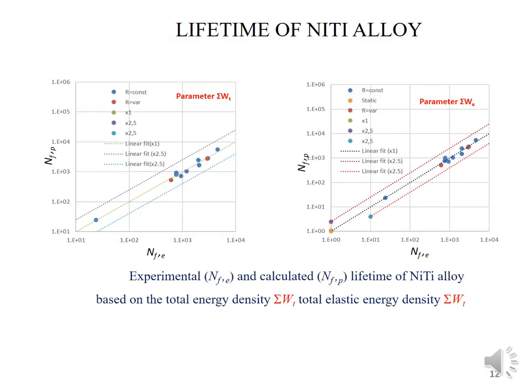Lifetime comparison of Pseudoelastic NiTi alloy, determined from experiment and calculated by the criterion of total energy density (left) and elastic energy density (right), is presented. The difference between these criteria does not exceed 0.6%, indicating the dominant role of total energy density in the fatigue failure of Pseudoelastic NiTi alloy under low cycle loading. Thus, the fatigue damage criterion based on total energy density can be used to predict fatigue life at constant amplitude, taking into account stress ratios.